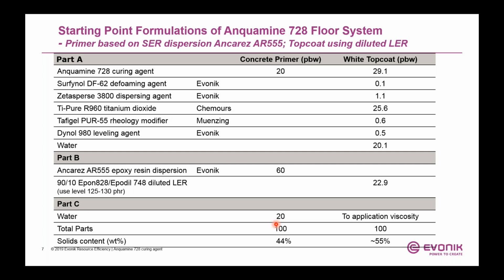Next, I'm going to show you the starting point formulation of the floor system based on Anquamine 728. For the primer, it's based on solid resin dispersion AR555, and the top coat actually uses the standard diluted epoxy resin. It's 9010. You can see here it's 9010, a standard bisphenol A type resin with diluent.